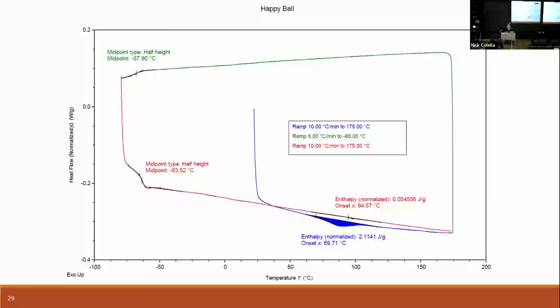That's very close. So you're right in that once we heat it up enough, it will lose its thermal history. So it can deform, it can melt, etc. We can melt crystallites, we can go through a glass transition temperature. We're basically erasing the thermal history. So when you prepare a sample, you can drop cast it, you can solvent cast it, or use other ways like spin coating. You could lyophilize it, you can freeze dry it, you can drop it into liquid nitrogen. There's a variety of ways of creating a solid film from a liquid to begin with.